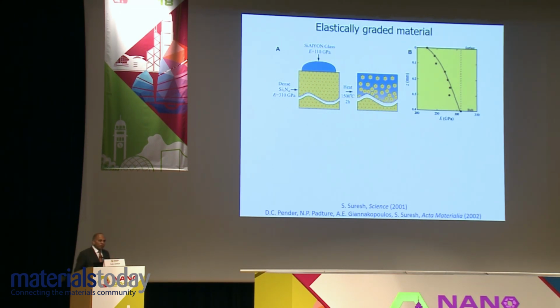Now you take this microstructure, and you take a spherical indenter, and you do the following experiment. You take just monolithic silicon nitride, take the spherical indenter, push it and indent it onto the silicon nitride, and you will get classic Hertzian cone cracks as expected for a brittle material. You do the same thing for glass, you will get exactly the same thing. You take a homogeneous material of the same composition as the surface composition of the graded material. Again, if it's a monolithic composite, then you will get the same Hertzian cone crack.